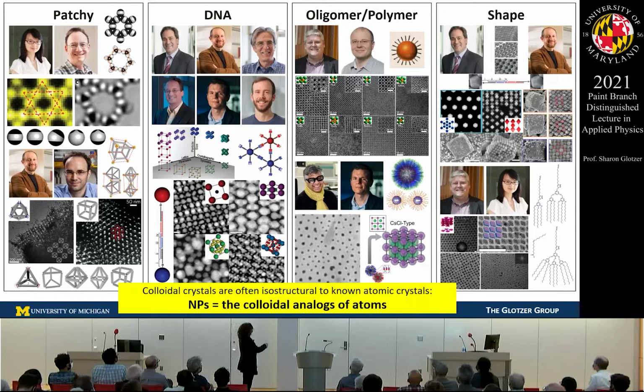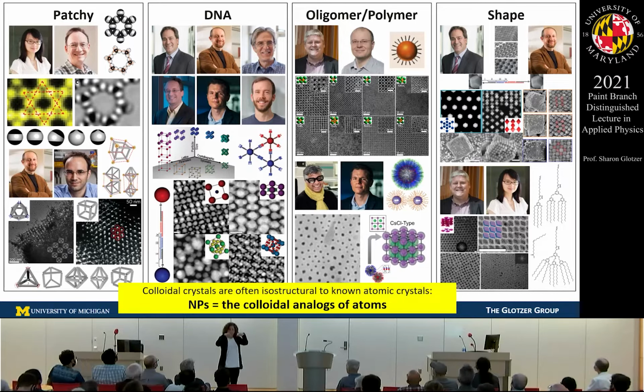Or you can use, again with complementary DNA, Chris Murray's group at Penn and Dmitri Talapin at the University of Chicago. They make different kinds of particles. They typically work with rare earths, and they'll make nanoplates that are typically maybe 10, 20, 30 nanometers, and they functionalize them with ligands. Now they're starting to use dendrimers to even further control the effective shapes of these things. And by doing that, you can get a lot of interesting structures, including quasicrystals, which I'll talk a little more about in a few minutes.